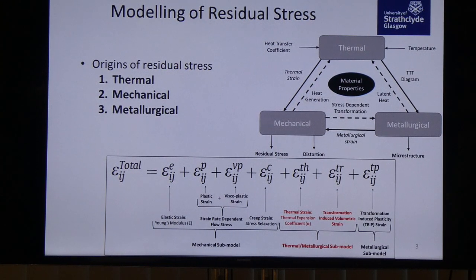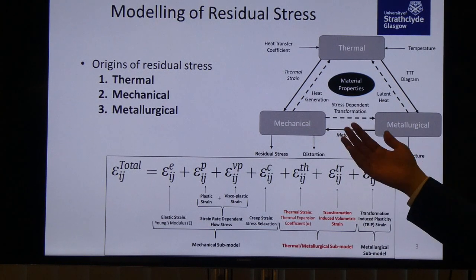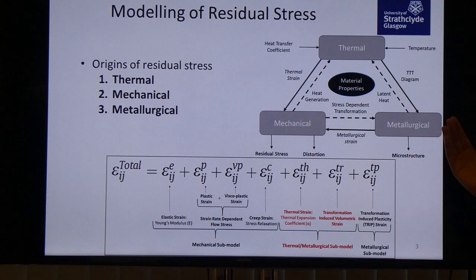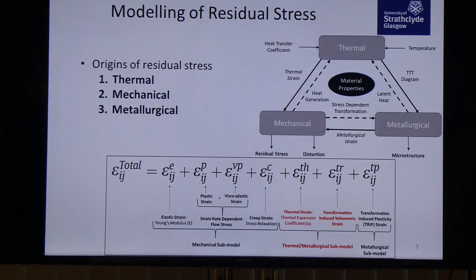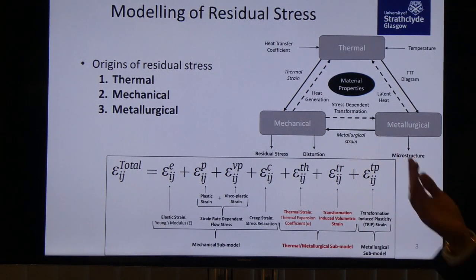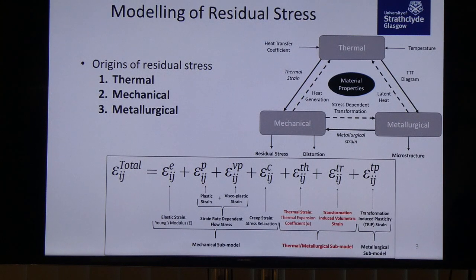In order to model this in finite element software, you consider the three origins of residual stress — your thermomechanical and metallurgical components — simplified into three interrelated sub-models. You can simplify interactions based on the process and material. For example, during heat treatment, heat generation is minimal, whereas in forging applications you might have to take that into account.